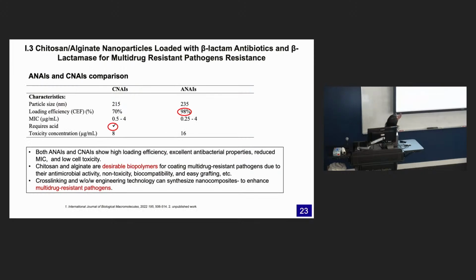We also compared chitosan and alginate, because chitosan itself is antibacterial. We recognized that the problem with chitosan is that to disperse it, you need to use acid. Mostly the results are very similar, but alginate gives much higher loading and encapsulation efficiency. That's important because these drugs, inhibitors and antibiotics, are very expensive. And it also doesn't require acid. So here we show high loading efficiency, excellent antibacterial properties, and reduced cell toxicity as well.